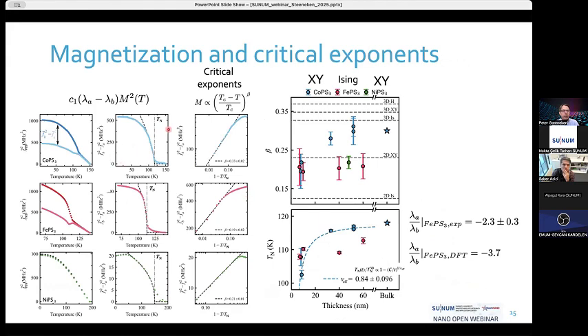So we use this technique to study different materials, not only this cobalt phosphor trisulfide, but also the iron and the nickel compound. And by monitoring the temperature dependence of this magnetization that we extract close to the Néel temperature, we can test what kind of magnetic order takes place. So these dashed lines here are different models for the magnetic order. And we can now, for each of these materials, see what kind of magnetic order there is in the material, but also how it depends on the thickness of the membrane. And we can also look at the Néel temperature, so the temperature at which a phase transition occurs. So we discussed with theorists, and we can also compare our results to some of their numbers. So the bottom number is the theoretical number, and this is what we found from our experiments. So there's still some discrepancy, so better theories are still needed to fully understand these measurements.